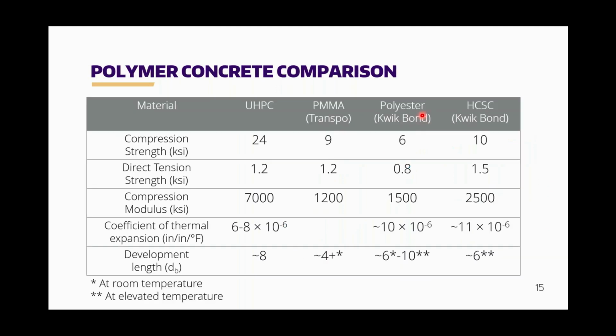So now, anytime I talk about polymer concrete, people ask me, so what are the material properties of this and how do they compare to UHPC, which is what we've been using for this particular application. So I'm showing you a comparison here of 3 commercially available polymer concretes and comparing them to a UHPC. And what you can see right away is that the compression strength is lower. It's closer to that of conventional concrete. The modulus is also lower, and this is now lower than conventional concrete, and that has to do with the different binders.